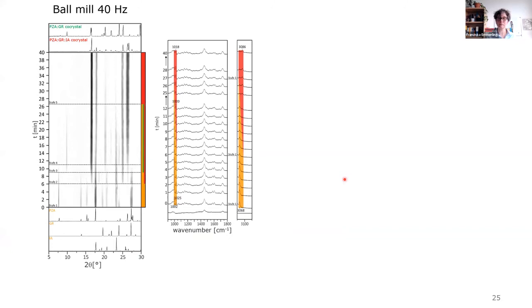So here you see again our top view of X-ray diffraction data, and we see the starting materials and final product. And here in green, you see in between, we have a formation of a binary co-crystal. In this case, it's not really good to distinguish between the formation of the binary and the ternary phase in Raman spectroscopy. We only see a pronounced change when we look at the pyrazinamide molecule, whether it is in the co-crystal form or not. So this is CH stretching that changes, and this is the bending vibration of the ring.